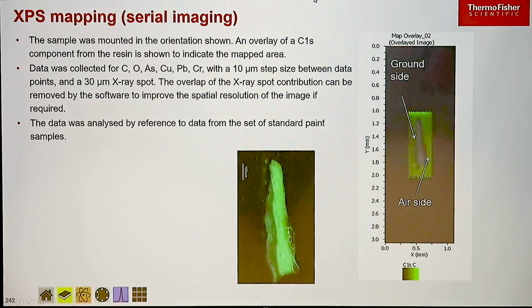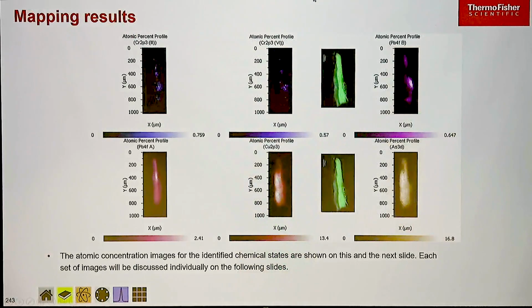So we got the sample then and put it into the XPS, and so we could just map over it just to show how it's aligned in the system. This is just a map of the epoxy around the chip. And then we could map it for the various different materials, so chromium-3, chromium-6. We found 2 different chemical states of lead, lead B and lead A. I'll come back to those in a moment, but you can see that lead B is really associated with that blister feature, which is about here. Lead A is associated with the little crystallites on the sample, and arsenic as well.